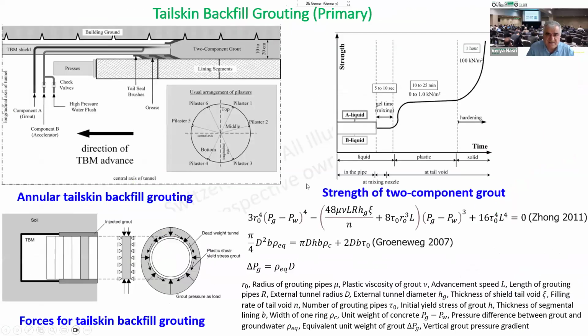So then we get to tail skin backfill grouting. Nowadays, two-component grouting is used, which at the beginning is liquid, then it mixes in a few seconds to gel, and then over, say, 25 minutes gets to 1 kPa, and in 1 hour about 100 kPa.